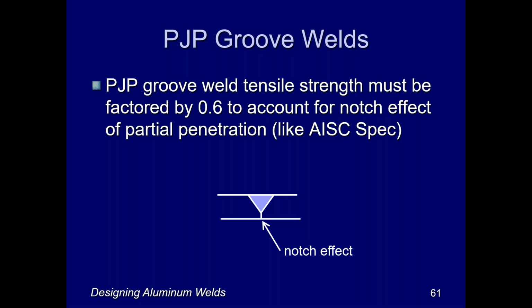That 0.6 factor, as I said, is just accounting for the notch effect of that potentially unfused metal at the root of the joint. And I strongly discourage you from using PJP groove welds for that very reason. You've got that factor that knocks your strength down, and the fact that you've got a built-in crack essentially at the root of your joint doesn't give me great confidence or hope for the future for that type of joint.